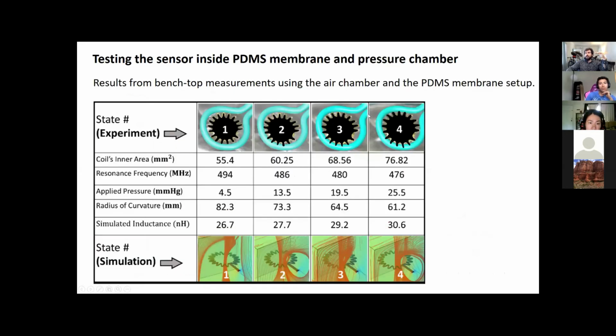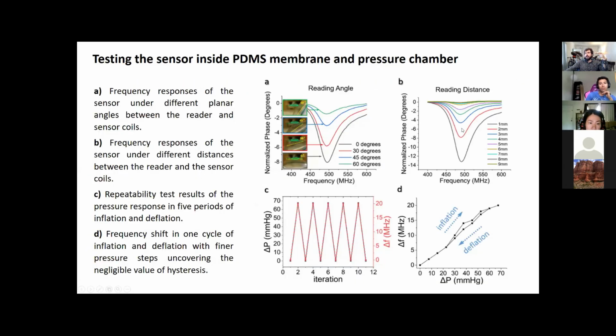So we are sure that the change in the reading distance doesn't affect the resonance frequency. And that makes you feel sure that when you have a change in resonance frequency, that's due to the change in the diameter of the sensor rather than the reading distance. And the same goes for the reading angle.